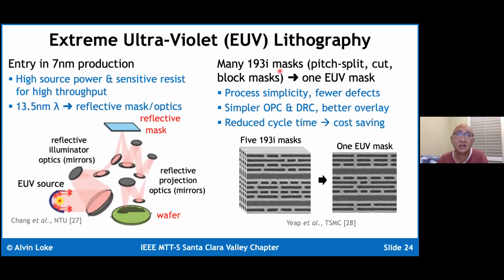With EUV, companies like TSMC have essentially used EUV to simplify their process. What would have been done with as many as 5 or 6 193 immersion masks, where you've got different pitch splits, cut masks that are even pitch split, and block masks, you can collapse all of that into a single EUV mask. You get better process simplicity because you're using a shorter wavelength. Your OPC is easier, your DRC is easier. You get better overlay because you have fewer layers you're trying to align. And the idea here is faster cycle time and cost savings.